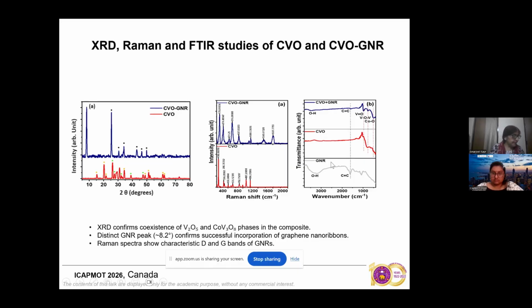Basically the XRD characterization of the synthesized sample confirms the presence of V2O5, that is around 33.7%, and CoV3O8, which is 59.23%. So both the phases are present in the CVO sample. Their relative phase contributions were determined through Rietveld refinement to find out this particular contribution. Then FTIR also confirmed the synthesis of our material.